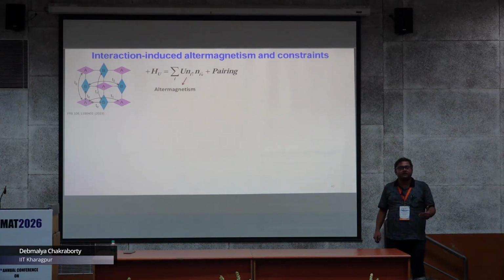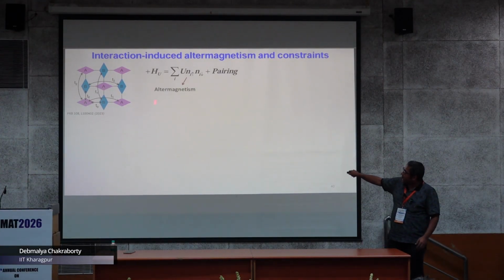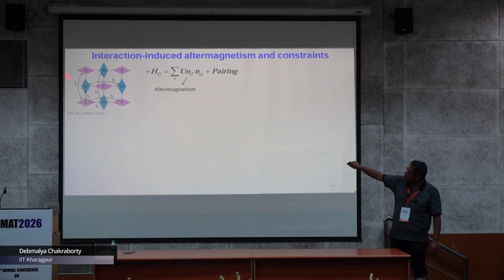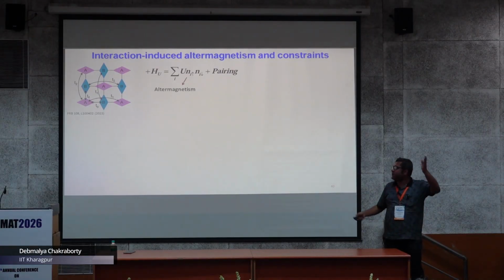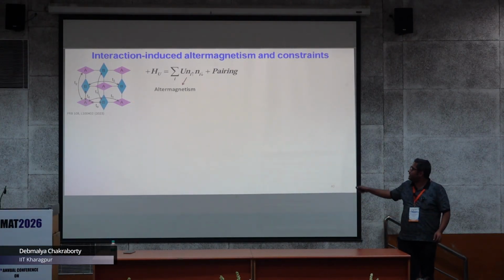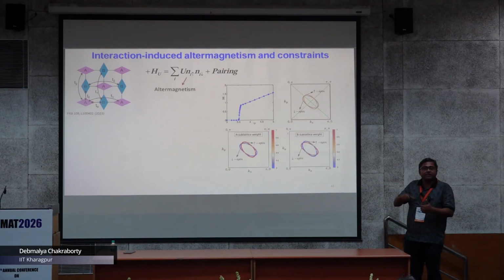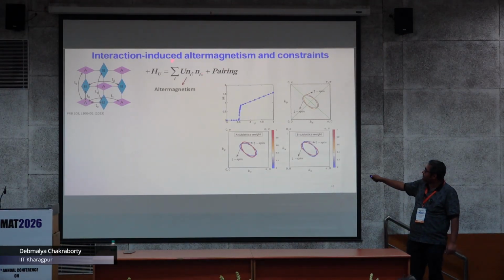Now I want to get altermagnetism from interactions. So I take a lattice which was proposed in this paper. We take this lattice with t1 not equal to t2, that means the hopping in x and y are asymmetric, which breaks the rotational symmetry, and we put a Hubbard interaction, do a mean field, and what we get is, if we look at the staggered magnetization M as a function of U, the Hubbard repulsive interaction, you see that if you keep on increasing U, you start getting M, and there would be some magnetism, and if you look at the Fermi surface, you will see that it's spin split, that means it's an altermagnet.